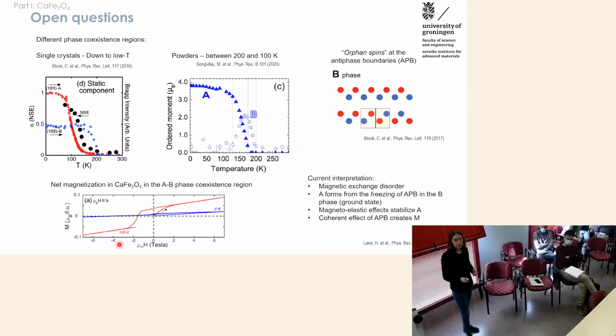And in addition, in a narrow temperature range around 120 K, there is the appearance of a net magnetization. So if we measure an MH loop, despite both A and B technically being antiferromagnetic, there is a net magnetization in the system. And it has been hypothesized that this can come from antiphase boundaries. If we look at domains of each phase, for example, here you see 2 domains of the B phase, the boundary between these 2 domains is actually the local structure of the A phase. So it has been hypothesized that the coexistence between A and B occurs due to the formation of a lot of these antiphase boundaries, which also carry uncompensated moments.